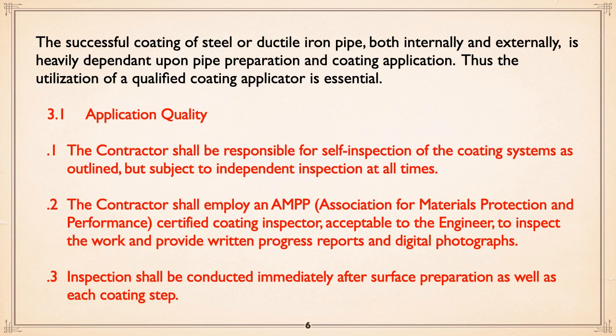Now, if you're going to coat steel or ductile iron pipe, internally and externally, the result depends heavily upon pipe preparation and coating application. Thus, you need a qualified coating applicator, somebody that knows what they're doing. And this is from specs that I used to use. Contractor shall be responsible and subject to independent inspection, shall employ an AMPP certified coating inspector. Inspection shall be conducted immediately after surface preparation as well as each coating step. After surface preparation, you want to move fairly fast to coating, and only an approved applicator shall be used. And list people that are in the business and have a good reputation. Having coating done by contractor Bob's uncle, unless he's a certified applicator, forget it. And again, have an inspector and a letter of verification upon completion. Coating is important.